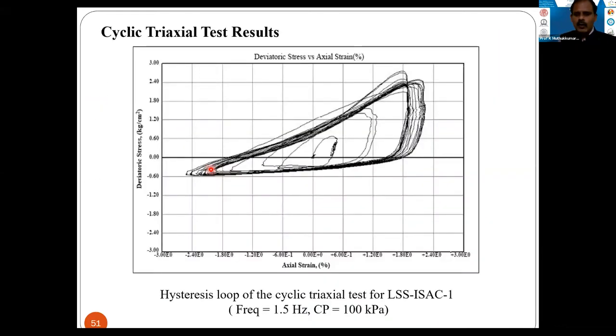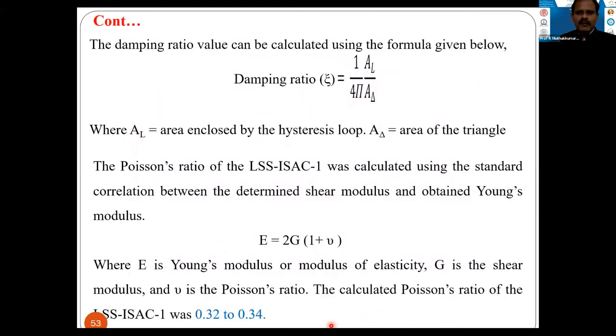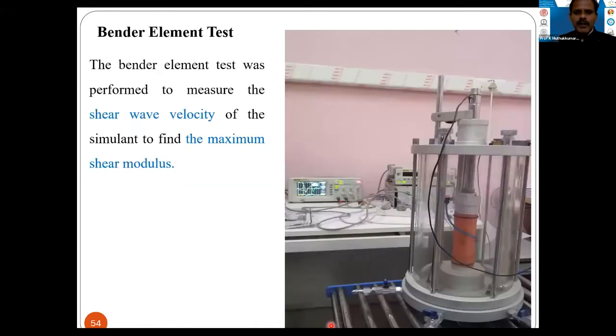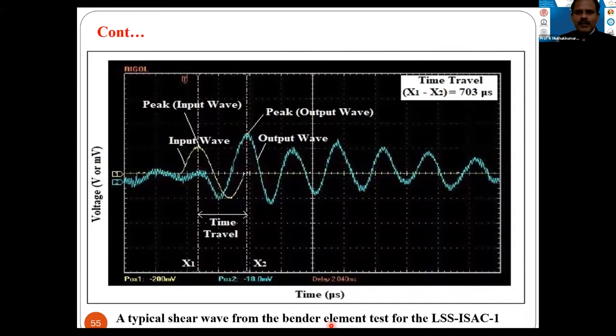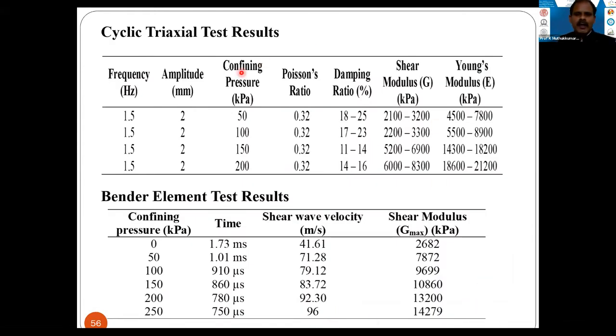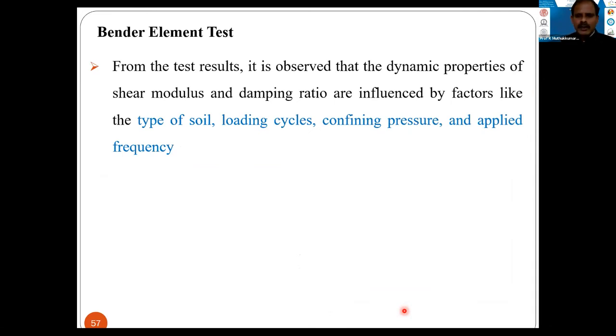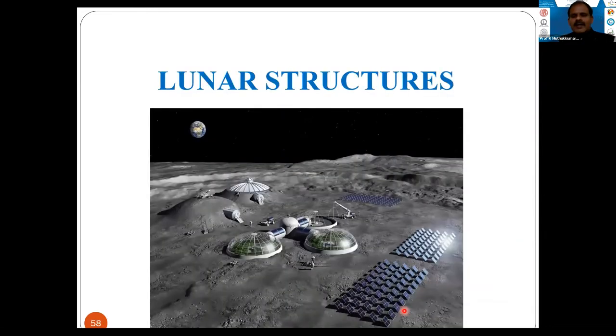And this is the complete hysteresis loop of this cyclic triaxial apparatus study for the frequency of 1.5 Hz at a confining pressure of 100 kPa. From this, we have calculated the damping ratio using the standard relation and using the E and G as estimated. From the Bender element, we have calculated the maximum shear modulus. And this is the complete outcome of this result for various confining pressures with the frequency for a particular value of the shear modulus, and the Bender element result for maximum shear modulus for the density corresponding to 65 as in the lunar reality. So with that, as I mentioned in the beginning, this study is still ongoing. So still, I'm in research in progress.